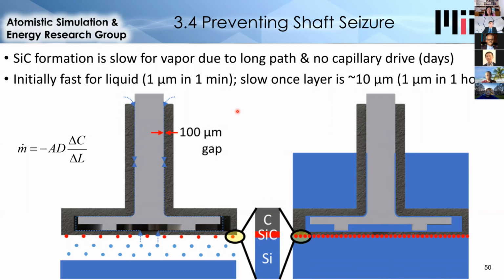One way to make it form slowly is to try to have it coated by gaseous silicon, so silicon that evaporates from the liquid and travels up into the pump body, just as it did in the experiment with the large tank. The problem here is that the flow path of the silicon is very tortuous. It's a narrow, long flow path. The gap is only about 100 microns.